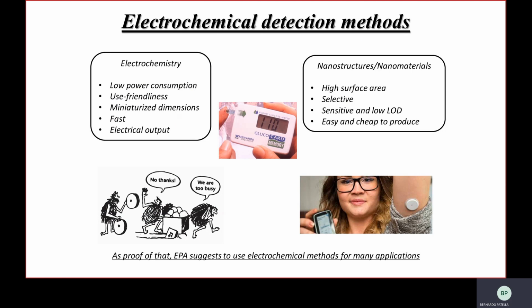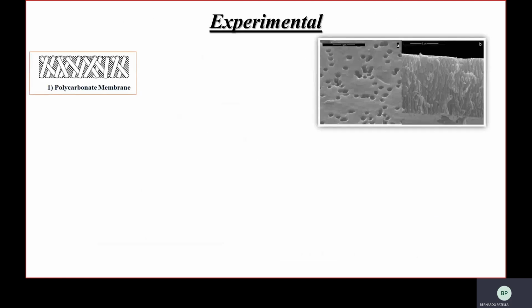Indeed, electrochemistry guarantees a low power consumption and small, easy-to-use instrumentation, while the high surface area of nanostructured electrodes can help to obtain sensors with high sensitivity, selectivity, and low limit of detection. In this work, we have developed a nanostructured copper electrode made of vertically standing nanowires obtained by galvanic deposition. A polycarbonate membrane has been used as template with nanopores of about 6 micrometers long and 0.2 micrometers in diameter. In the same image, we can see the top view and the cross-section of the template.